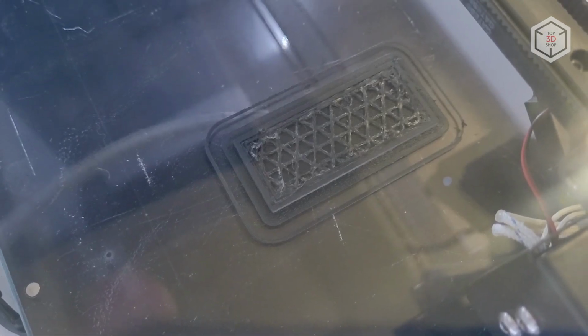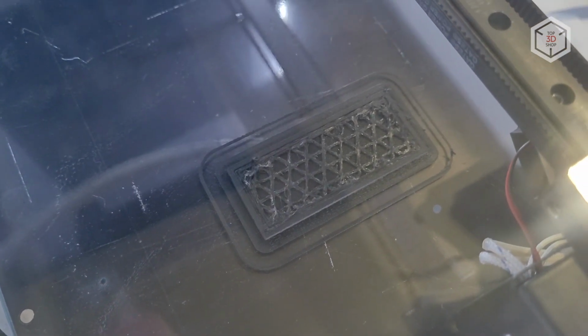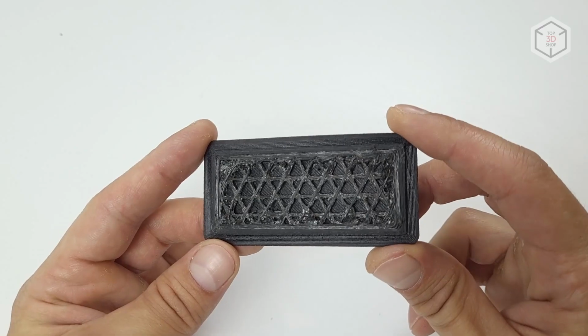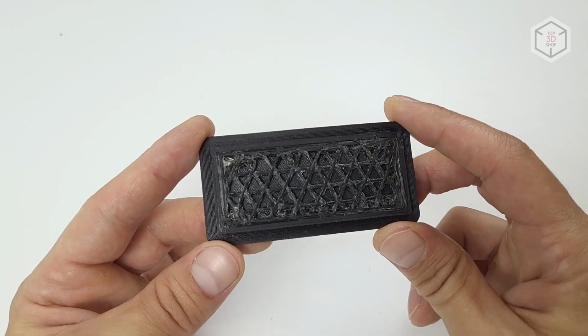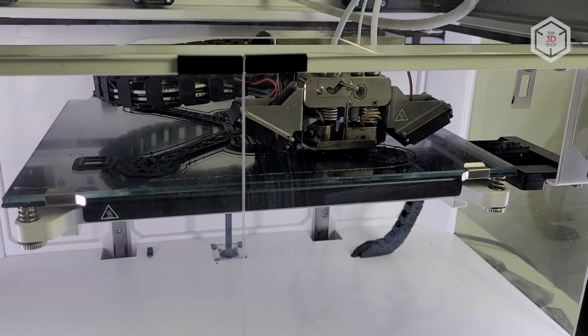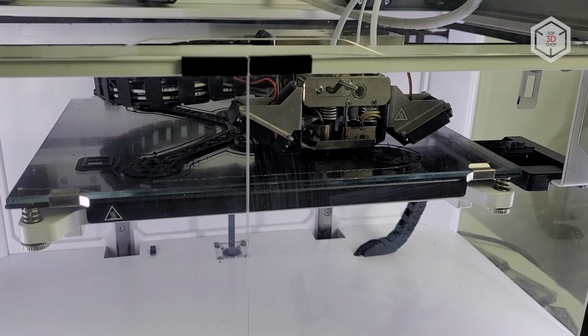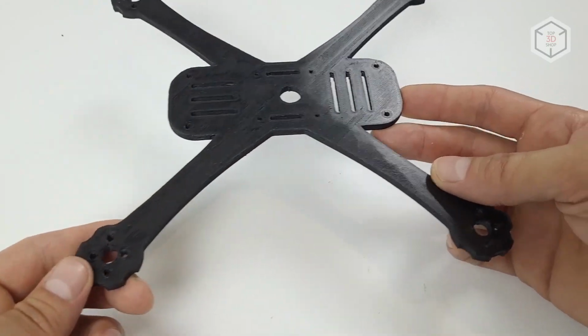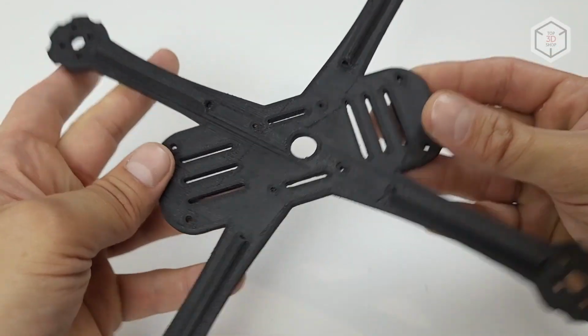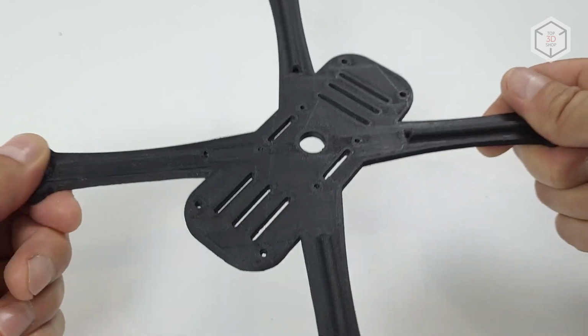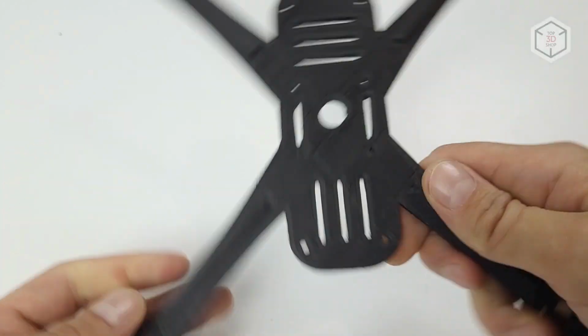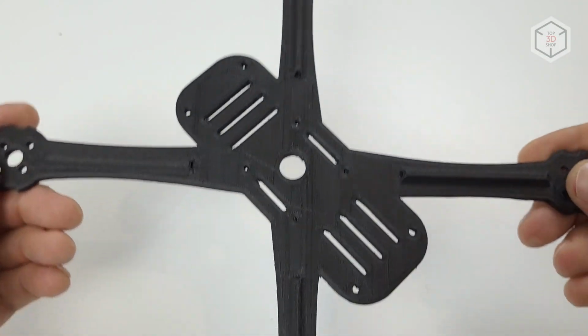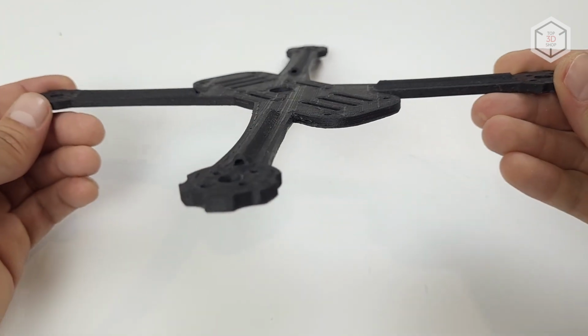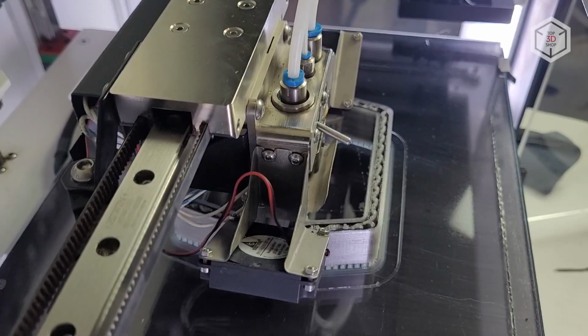First, we printed a small test rectangle, and it turned out that such a combination worked quite well. The reinforced infill and contours laid on the ABS without any problems. So we tried printing a small frame for a racing quadcopter in the same manner. All went well. The frame was printed out, the fiber laid well, and the covers closed. The experiment can be considered a success. The only thing to keep in mind is that for such experiments with materials, you need Aura with the open or at least Ext license.